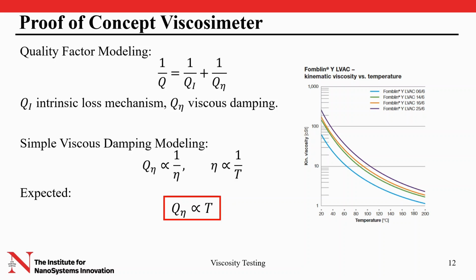Viscous damping is a very complex phenomenon, but in the first approximation, we can assume that the quality factor due to the viscosity is inversely proportional to the value of the kinematic viscosity itself. In this case, we used fomblin oil from YLVAC, and we can see the dispersion curve for the kinematic viscosity as a function of the temperature, which is in turn inversely proportional to the temperature. Neglecting other sources, we can summarize the total contributions to the quality factor as the inverse sum of the intrinsic losses due to the resonator and the viscous quality factor. Therefore, what we can expect in this very simple, straightforward model is a linear relationship between the quality factor and the temperature.